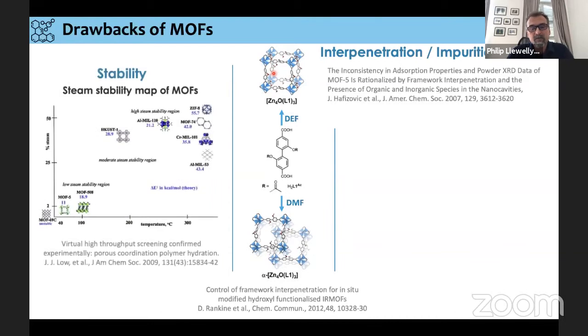The second thing we have to worry about is that because we have such a wide spectrum of materials in terms of chemistries, in terms of linkers, et cetera, we also have an equally wide range of properties. And of course, many materials will be stable and others maybe not. So one of the things that was seen quite initially, some of these initial materials, and here we have MOF 5 down here, are actually not so stable to steam, for example, or to temperature. And so one of the things that we have to be careful about is the stability of these materials.